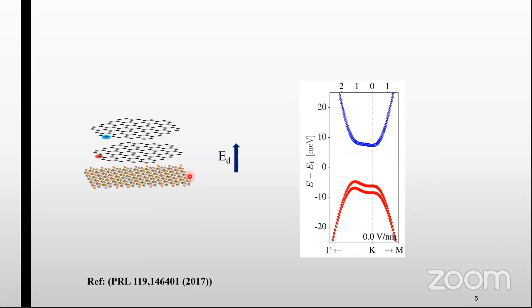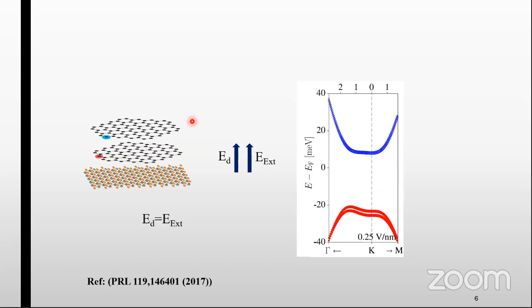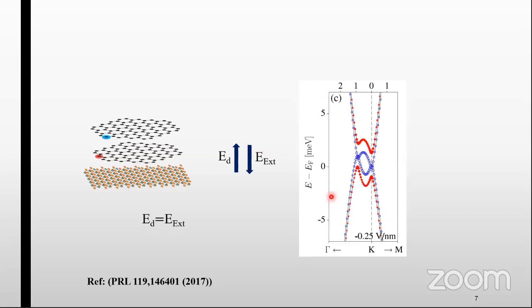So we understood that for bilayer graphene and single layer WSe2, we will have this kind of band structure where the valence band will be split because the bottom layer of bilayer graphene will experience higher spin orbit coupling as compared to the top layer. If we apply an external electric field to the system in the same direction as the intrinsic electric field, then the band gap for this dispersion will be enhanced. But if we apply a field just opposite to the direction of the intrinsic electric field, and of the same strength, then these two layers will be at the same potential and the band gap will close.